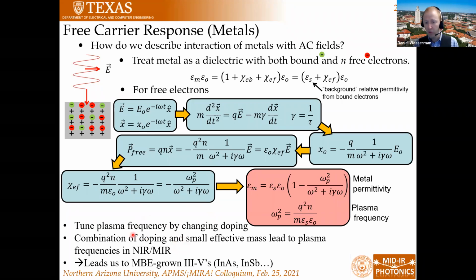And so we can tune the plasma frequency by changing the doping. If we have narrow bandgap semiconductors, which can have high doping and small effective mass, that means we can push the plasma frequency into the mid-infrared. This leads us to a class of materials: epitaxially grown III-V semiconductors, particularly narrow bandgap semiconductors such as indium arsenide or indium antimonide.